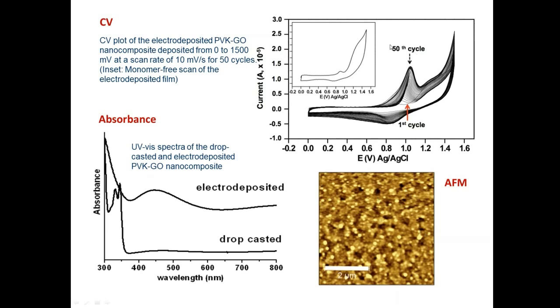We can follow this electrodeposition process by looking at the cyclic voltammogram up to 50 cycles. We can see here the oxidation and reduction wave. As we deposit the film together with the polyvinyl carbazole, there appears a peak at the 400 to 600 region, indicating the polymerization of the carbazole units to form polycarbazole, whereas a simple drop-casted unit without the electropolymerization process only shows the carbazole peak, as here.